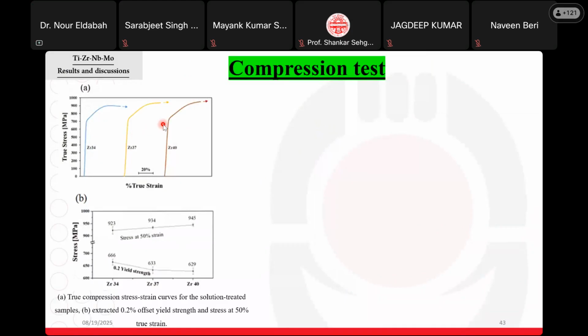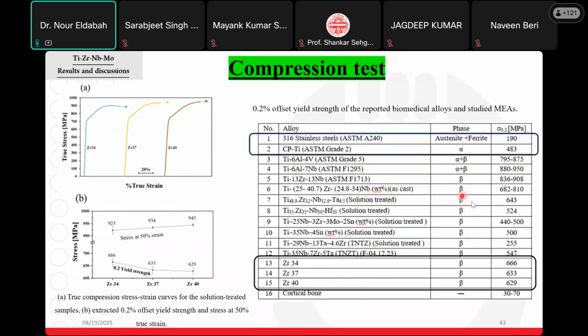We have accomplished the compression test because orthopedic implants are exposed to compression loading all the time. You can find that a plastic deformation flow occurs after the yield point for all the designed alloys. So our alloy has good ductility with a high value of yield strength, and this was recommended for us. It is higher than commercially pure titanium or 316 stainless steel, and more than some of the traditional titanium alloys.